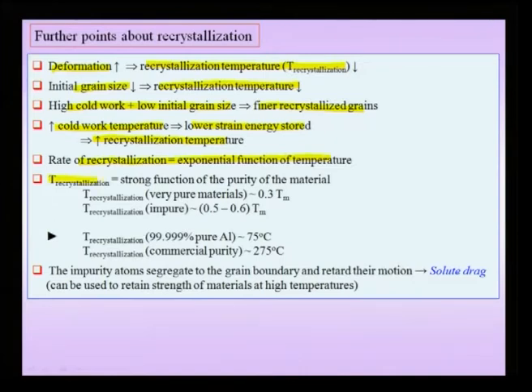The recrystallization temperature is a strong function of the purity of the material. Suppose I take the recrystallization temperature of very pure materials, it is of the order of 0.3 Tm, but suppose I take an impure version of the same material, it is between 0.5 and 0.6 Tm. For example, if you take pure aluminum, which is about 99.999% aluminum, the recrystallization temperature is about 75 degrees Celsius. But suppose I take commercial purity aluminum, which may have other impurities, then the recrystallization temperature increases to about 275 degrees Celsius.